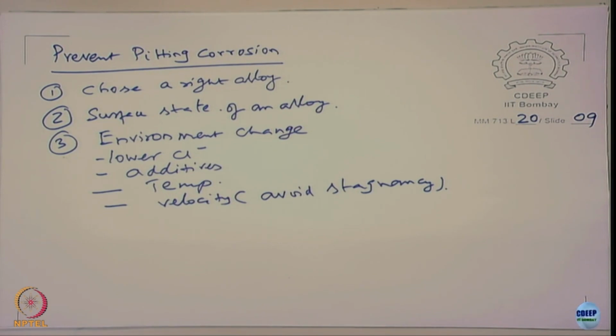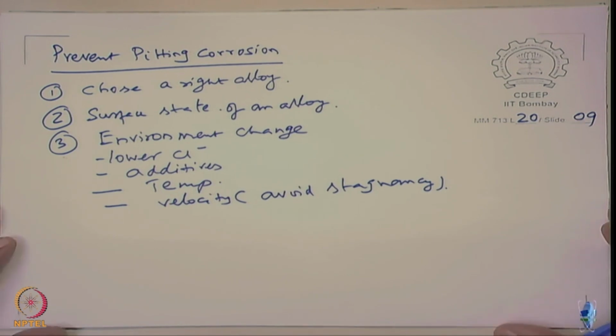We said that pitting corrosion can be prevented by, of course, choosing the right alloy. Of course, that is a very generic way of talking about it. You also need to look at the surface state of the material, how polished it is, and the environmental changes: chloride should be reduced, you can add additives, you can lower the temperatures and you avoid stagnancy and all. But of course, the material selection depends upon what? Depends upon a given environment, right. You know the temperature, you know the chlorides, you know the pH conditions, and so you decide what alloy is suitable for that.